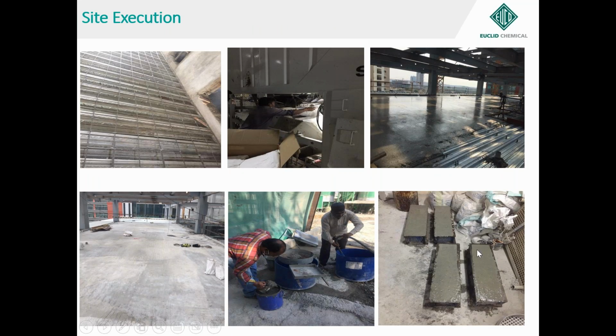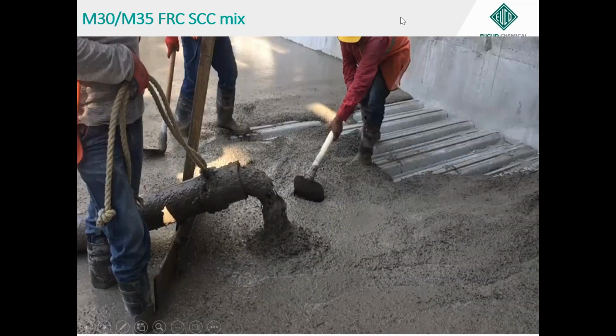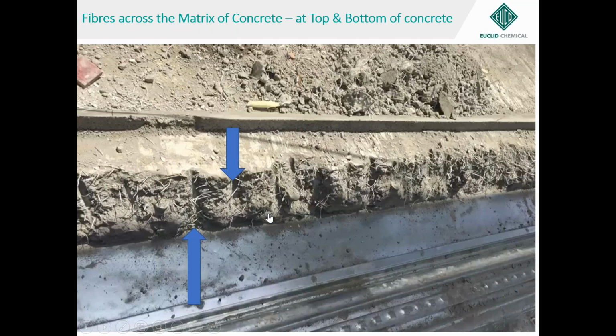So these are the processes, these are the beams. People wanted to understand the way fibers are calculated per cubic meter. It was weighed, cleaned, washed, weighed again, and seen that it is falling within 10%. This was an M30 SCC mix, FRC. You can see the fibers from the bottom of the concrete to the edge, from top to bottom. The spread of properly added fibers can give you a great high performance fiber reinforced self-compacting concrete. I just want to show you a small video of how the testing in the laboratory has to be done, just to get a glimpse of this.